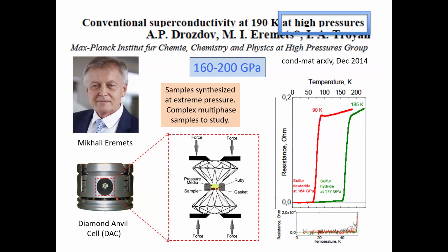And the diamond anvil cell, so it's called, that encloses all this, looks like this, and it's roughly an inch in dimension. And if you want to crank this up to 200 gigapascal pressure and take it to a synchrotron, you could put it in your pocket and get on the plane. I don't think you put it in your pocket because there's a fair amount of energy stored in there, but you can, that's the size it is.